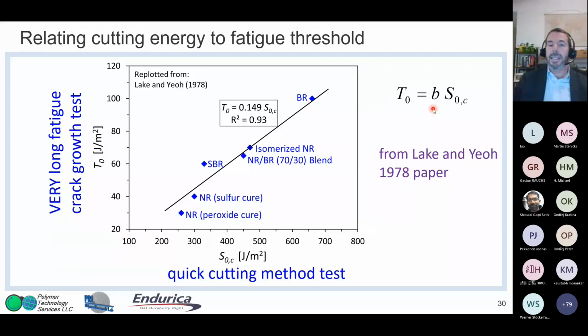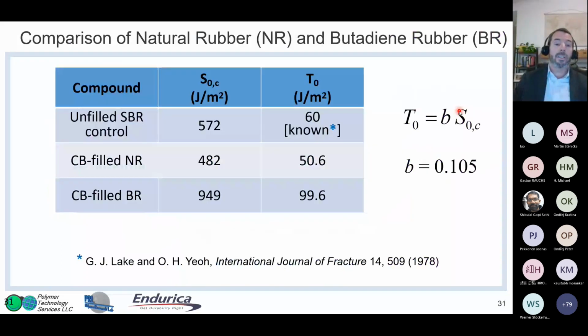So one of the key things that's needed in this method is a control material for which you know T0, and then you can measure S0 using the same conditions in your other experiments. So that was done here. So I showed you the data for carbon black filled natural rubber and butadiene rubber, 482 and 949. Our control material was an unfilled SBR. It had a value of 572 and had a known T0 of 60. So based on that known value of 60, we can determine B. That can then be applied to the other two materials.